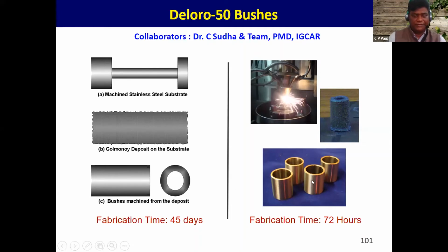After that, we went for additive manufacturing instead of conventional manufacturing. We gave a helical upward motion. Once we finished this deposition, we did a small machining, and it helped make things happen. The job which was being done in 45 days could be completed in 72 hours. So this is a big change that additive manufacturing brought into the domain.